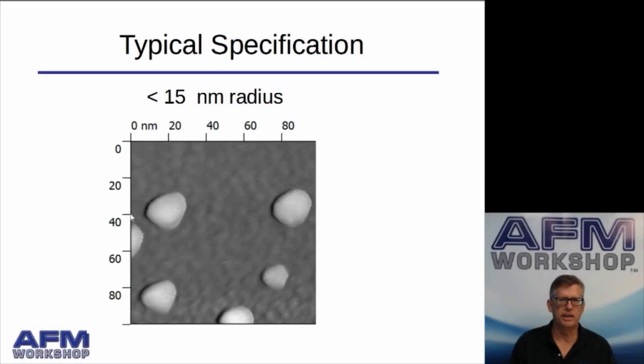This is an example right here of a general purpose AFM probe with a specification of a radius of less than 15 nanometers or a diameter of less than 30 nanometers. And these are 1 nanometer and 3 nanometer nanoparticles. And you see on the scale right here that this is 0 to 100 nanometers. So the shape of these nanoparticles is being broadened by the geometry of the probe. However, if you look at the height of these, it is correct.